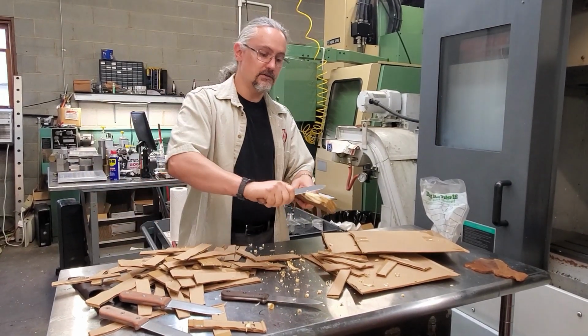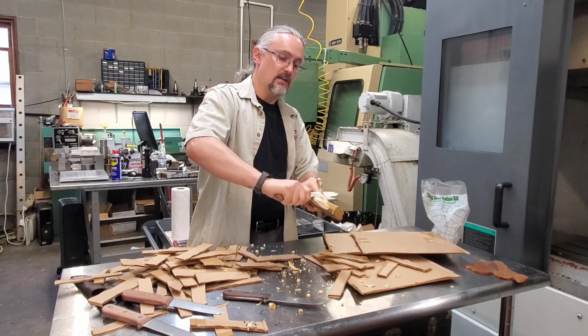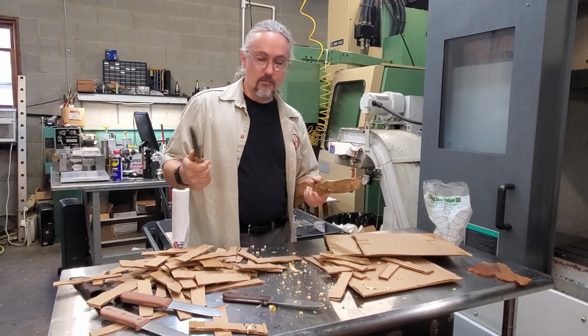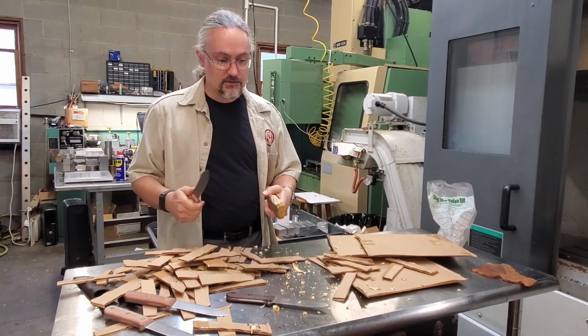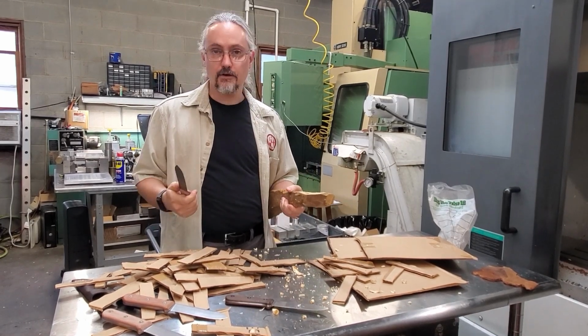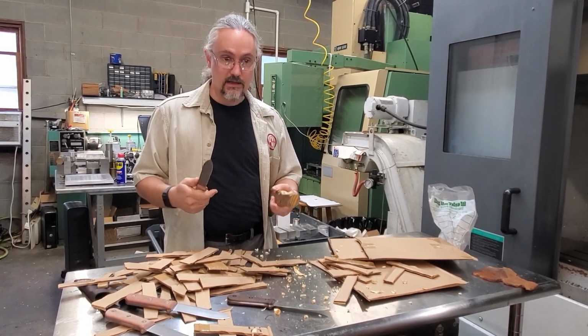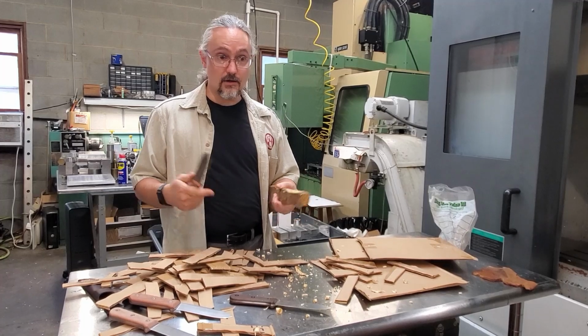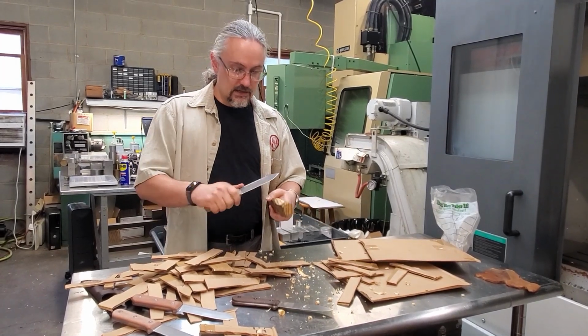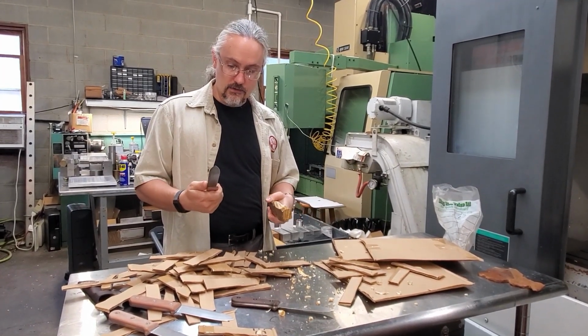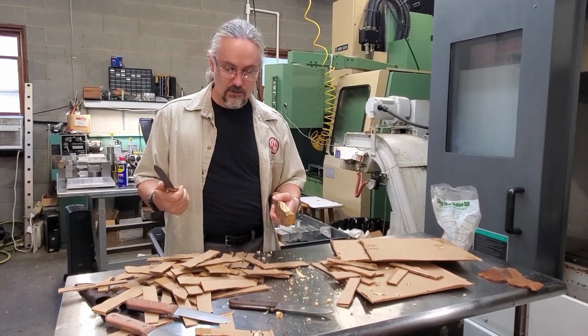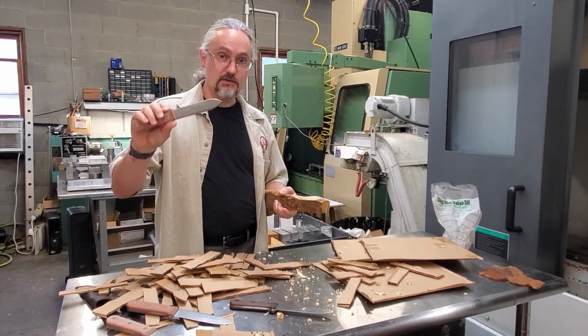And so the Delta heat treat and any of the low temp tweaks, if done correctly, can improve your edge stability, because you've got harder martensite. There's more carbon in your martensite. You've got slightly finer carbides because you're not developing as many secondary carbides and you're not growing your primary carbides. And because you're addressing retained austenite in the quench, you've got a little bit more of a homogeneous microstructure.